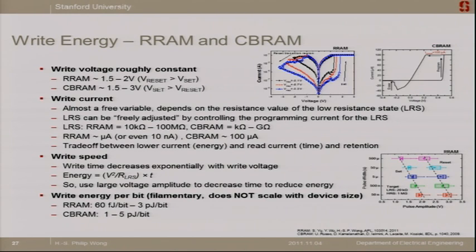So the energy is V squared divided by R of the low resistance state, times the time. If you increase the voltage, then you're increasing the square, but the time goes down exponentially. So if you want to consume low energy, you would use a large voltage amplitude to decrease the time to reduce the energy. Okay, so you do that. Of course, you cannot do that without bound. If you increase the voltage very high, then of course you kill the device, right? So there are some bounds to it.